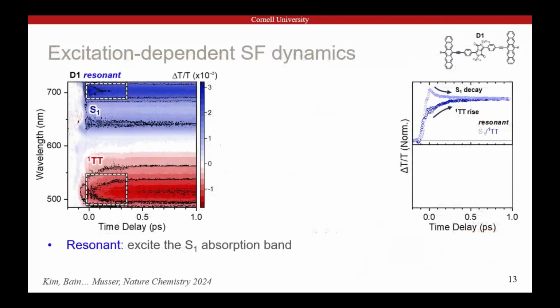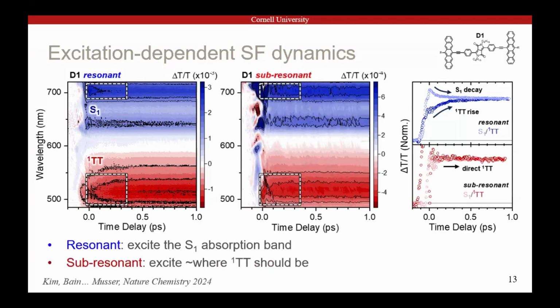So what follows is a ton of pump probe spectroscopy, but the data maps onto a very simple interpretation. This is typical transient absorption spectroscopy on a normal singlet fission material. We have a signature of the singlet up here that decays, photoinduced absorption of the triplet pair down here that grows in. When we photoexcite with a 10 femtosecond pulse, we can see very smooth conversion between the singlet and the triplet pair. So this is typical singlet fission behavior in a strongly interacting pentacene system over a couple hundred femtoseconds.